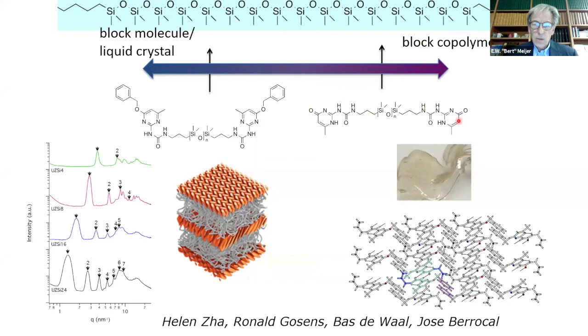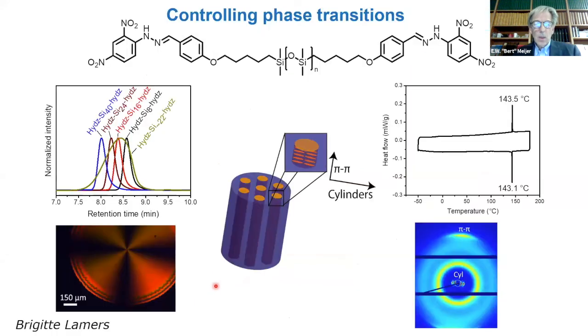However, the precursor of this unit crystallizes in 2D. And here you see a cartoon, and here you see the reflections on X-ray. And now the length of this spacer only determines the distance between these layers. So this looks like a smectic-like liquid crystal, while it is actually still a normal material. And this work was done especially by Helen Zha. Now, Brigitte showed that it really gives you perfect materials, this siloxane and these hydrazones. And I hope you can appreciate that the material has a melting point that is so sharp, you can make domains as large as centimeters in which all of the cylinders are perfectly aligned with respect to each other, almost like a crystal, but it remains a polymeric material.